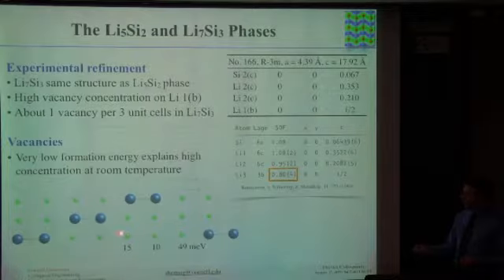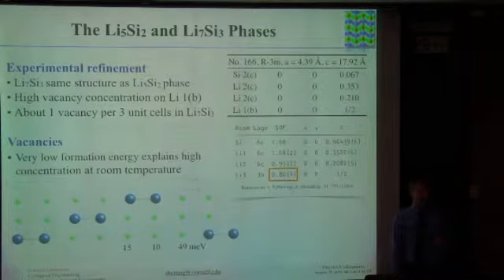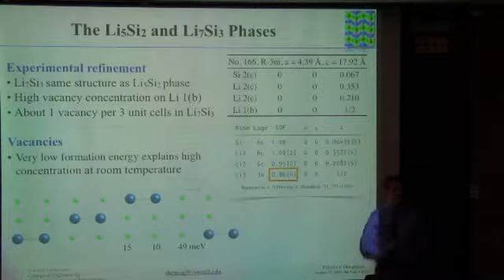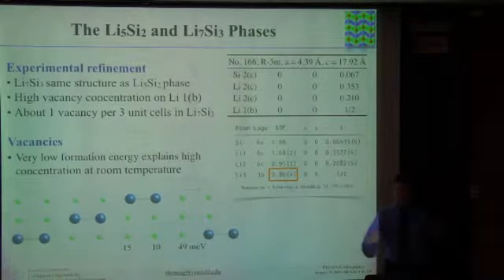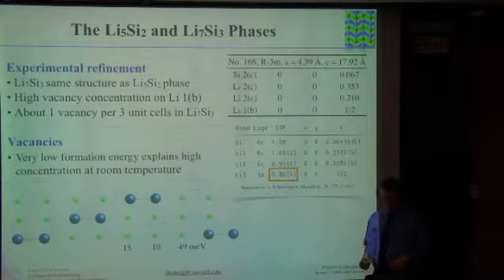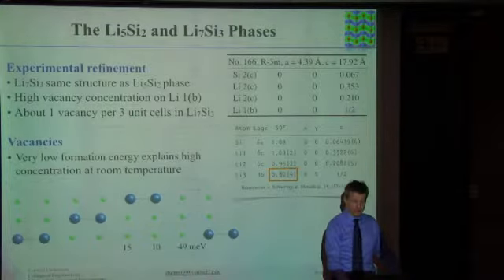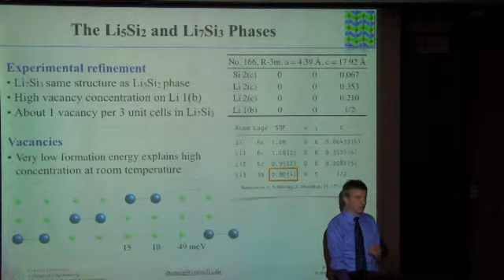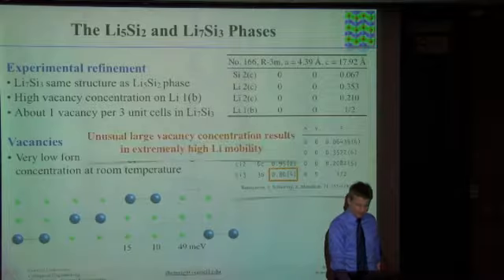So even at room temperature, we have very large vacancy concentrations in these systems, somewhat unusual, which is actually in this case a good thing, because large vacancy concentrations means the lithium is very mobile in these structures. And so it tells you that lithium could relatively rapidly diffuse in these systems and change the concentration during lithiation or delithiation running the batteries. So we didn't quite find a completely new structure. We found one which was defect-free. At room temperature, it's going to have a lot of defects in it.